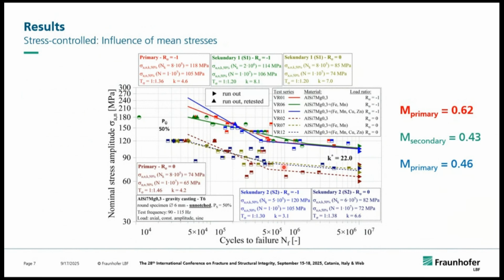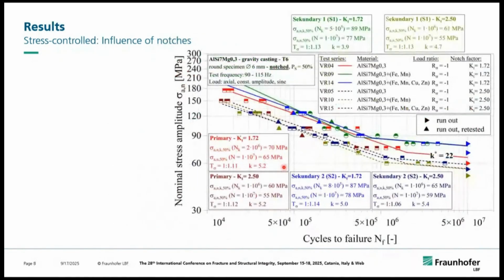Even in the tensile loading, we could see a slight improvement. This might be a bit related also to the scatter band, but nonetheless, it seems that the secondary alloys, due to the iron and copper content, improve a little bit in fatigue strength in the tensile loading regime. So we could not see that there is generally a loss in fatigue strength for those alloys.